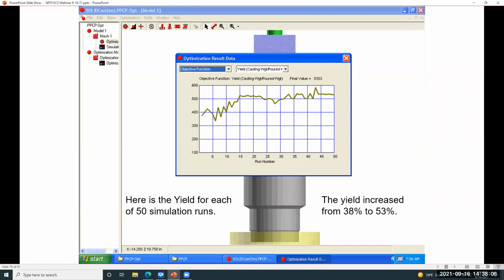So originally when this happened, that was an overnight run. This was an example we did a number of years ago. With today's computer, you could probably do those same 50 simulations in a couple of hours. This shows the summary. The initial situation, we had a process yield of about 38%. The final yield was 53%. So we had approximately a 15% improvement in yield.